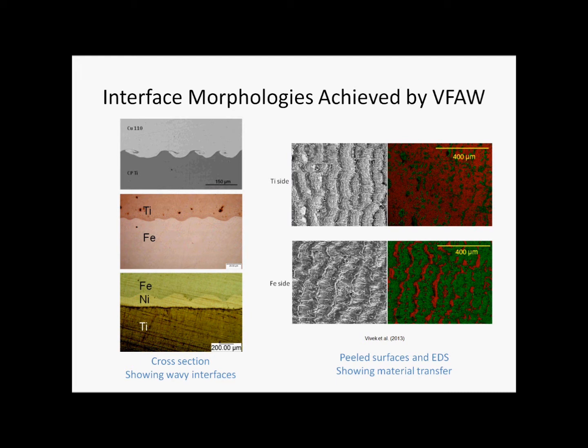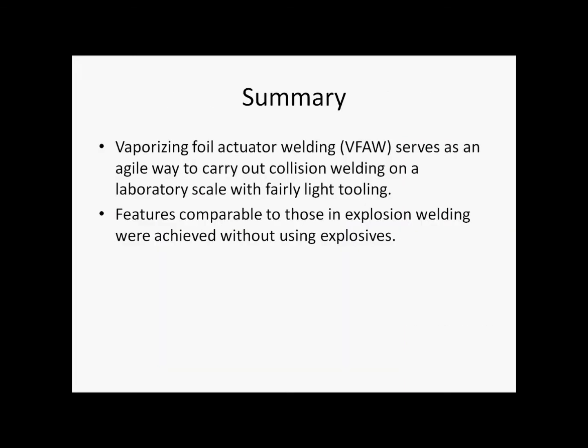The joints exhibited fair strength, as revealed by peel testing, and material analysis of the fracture surface shows material transfer across the interface, proving that the joint failed in the parent materials and not just along the interface. In summary, vaporizing foil actuator welding serves as an agile way to carry out collision welding on a laboratory scale with fairly light tooling. Features comparable to those found in explosion welding are achieved without using explosives.